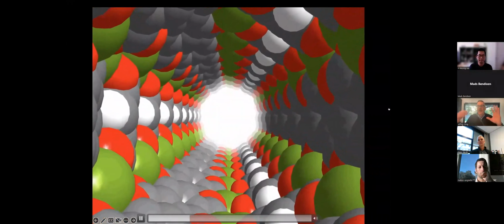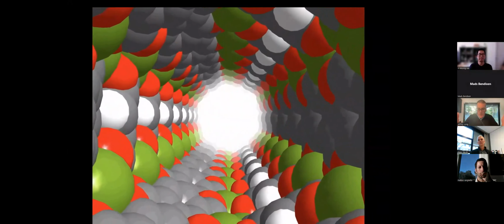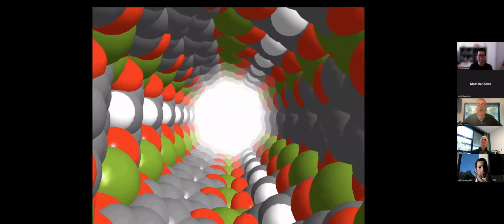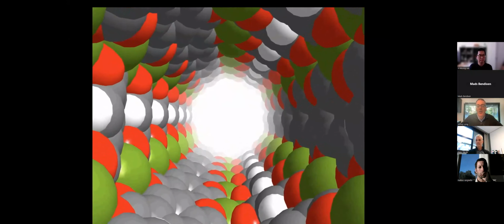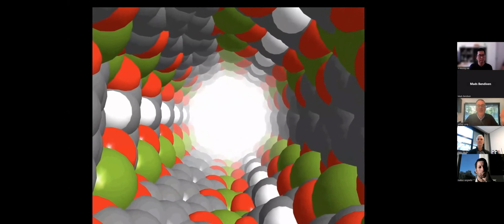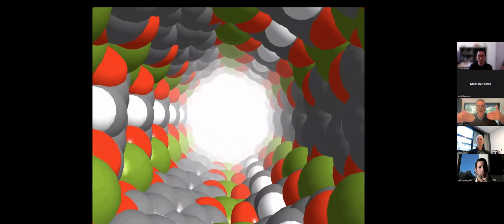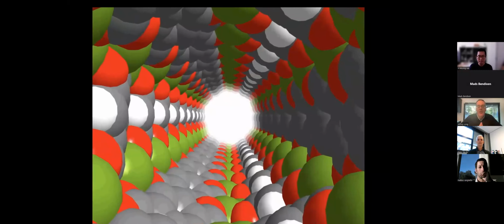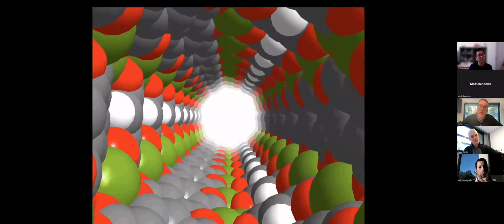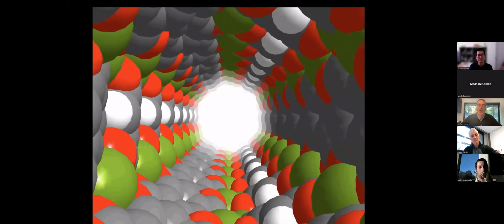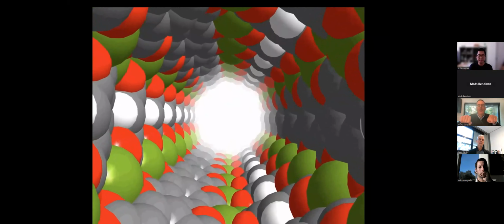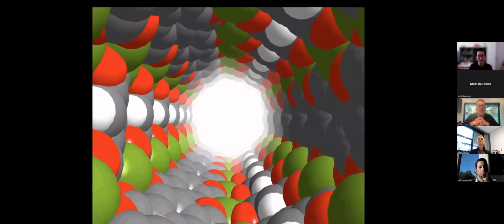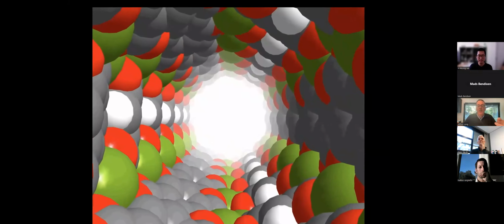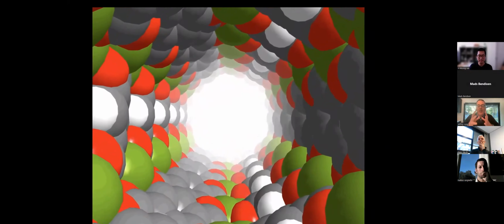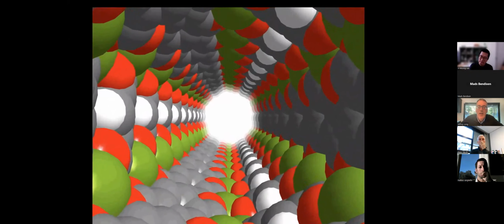And if you were a CO2 molecule and you approached a crystal of this MOF and you entered one of the channels, then you'd have a view like this. So this is looking down one of those channels. And the green spheres that you're seeing are the magnesium cations. And so you can see at the corners of the hexagonal channel, you have rows of magnesium 2+ centers. And those magnesium centers are spaced about 6.5 angstroms apart.